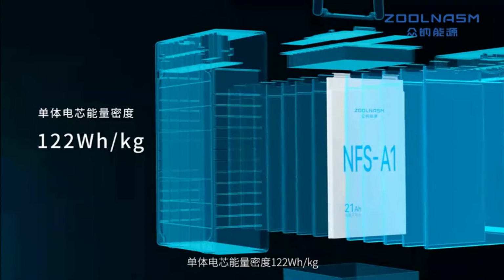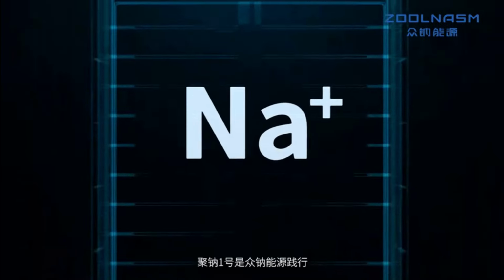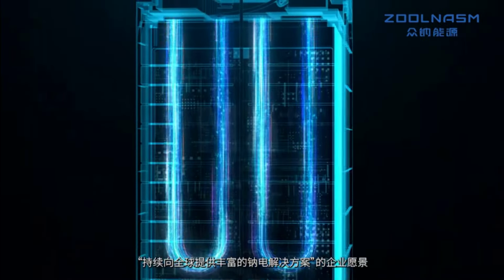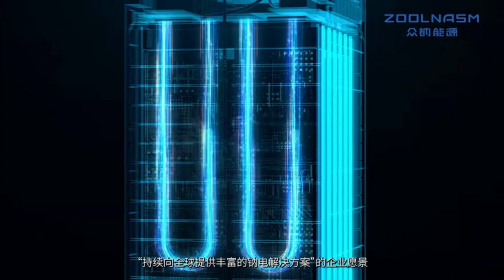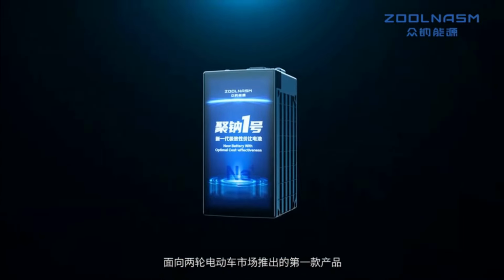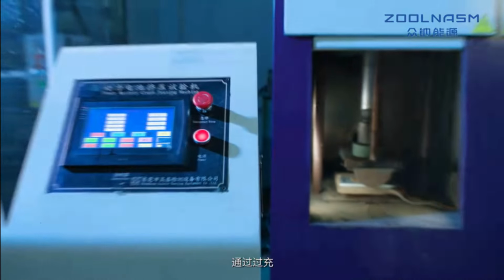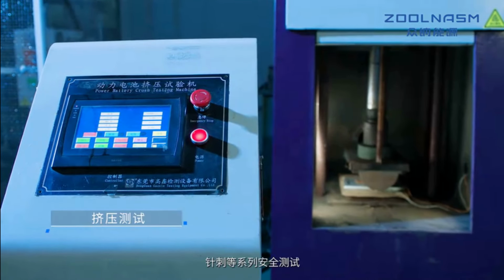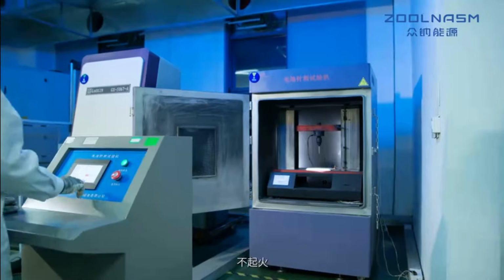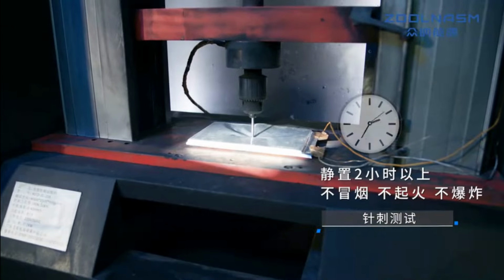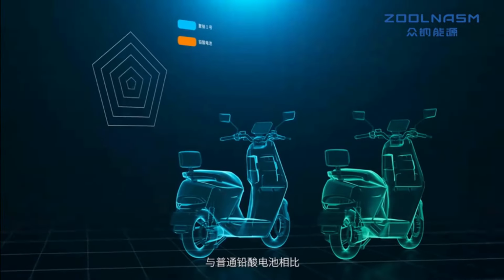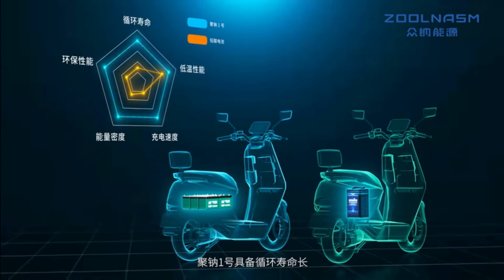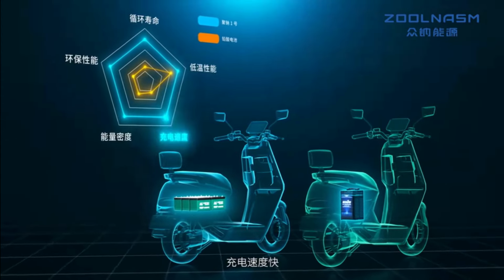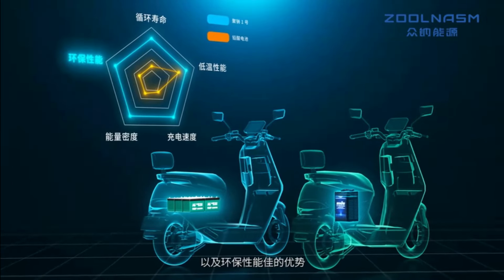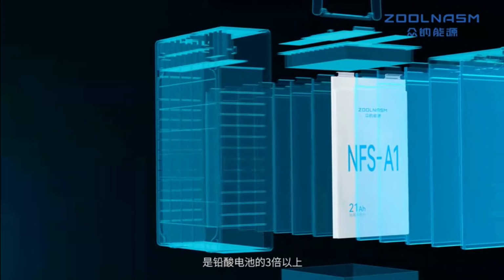It uses a polyanionic sodium ferric sulfate cathode material, and it does not contain precious metals such as copper, nickel, vanadium, which means it will be much cheaper to produce. The soft pack sodium-ion battery developed by ZHONGSODIUM Energy successfully passed the challenging needle puncture test for the currently commercially available lithium-ion batteries in a third-party authority and did not smoke, fire, or explode throughout the process. In actual use, the battery will not penetrate when there is a short circuit, and the needle puncture test directly pierces the battery, and in such an extreme case, the battery can still remain stable, which can indicate that in case of internal short circuit, the battery safety is higher.